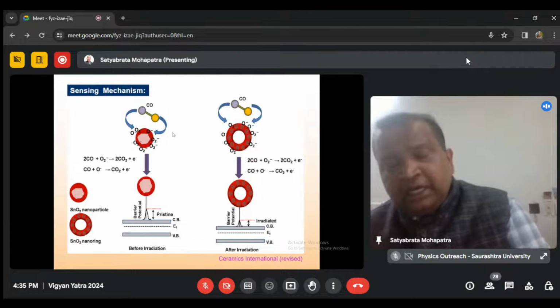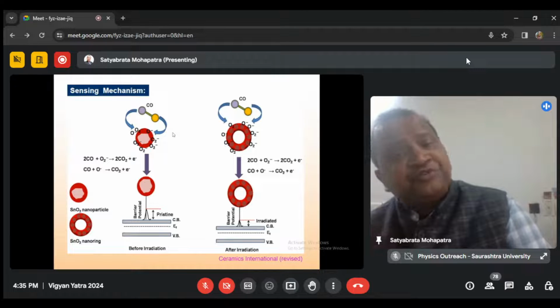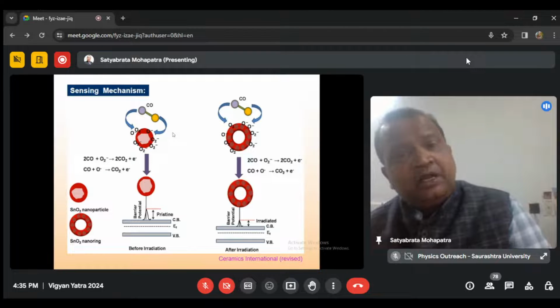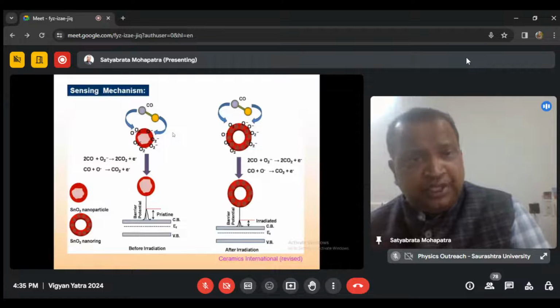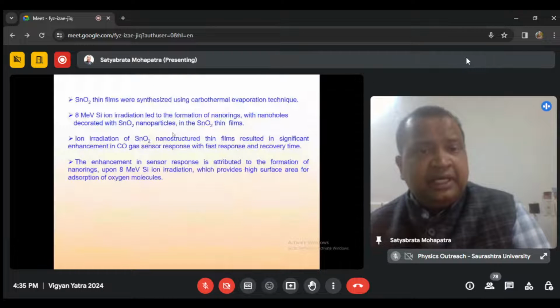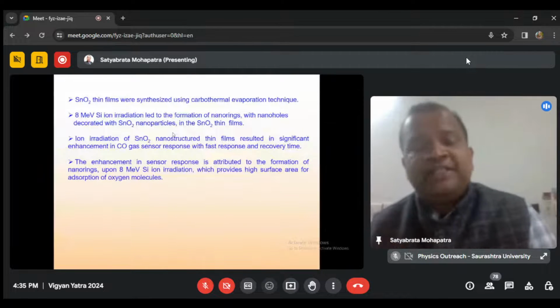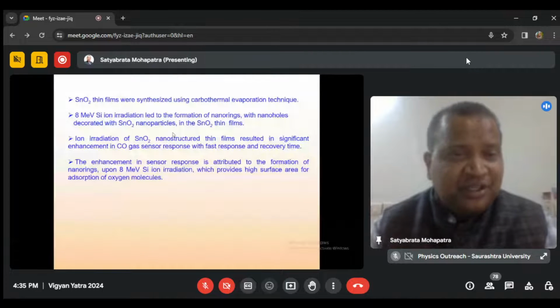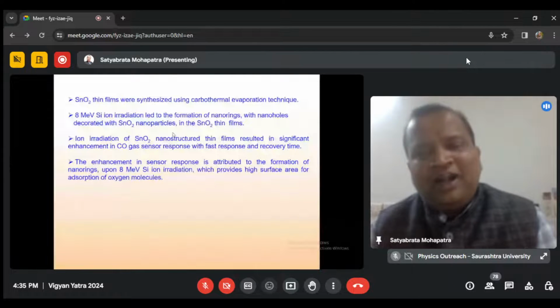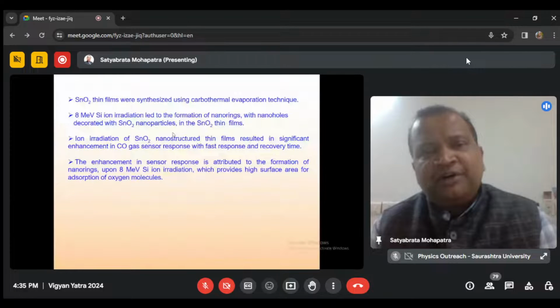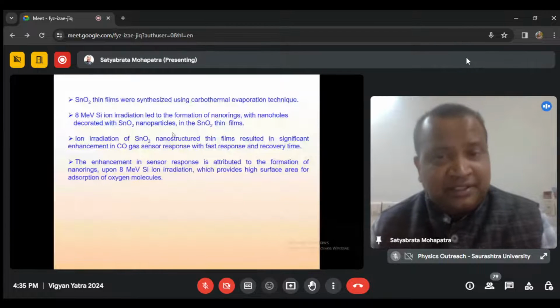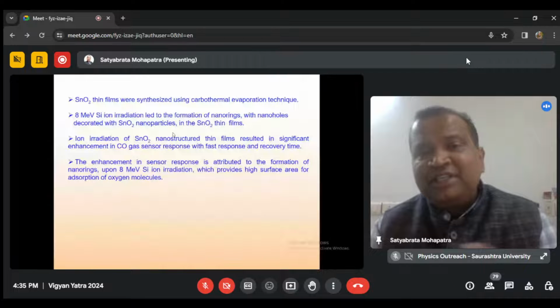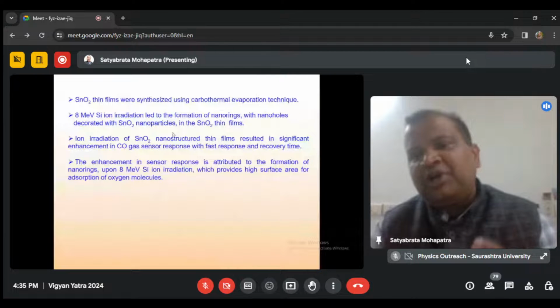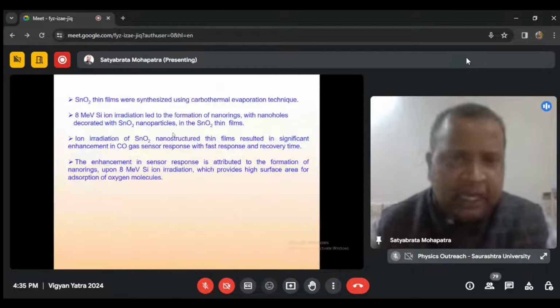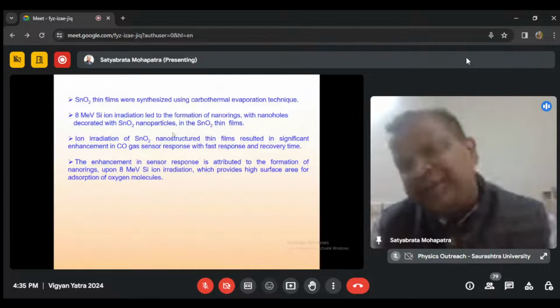So these are basically gas exposure driven resistance changes, and now it's a question of tuning the crystallites, having the right mix of crystallite size, porosity, and defect concentration, which is required for the development of very efficient gas sensors. And you can sense a toxic gas like carbon monoxide, a lethal gas, with very high response and selectivity.